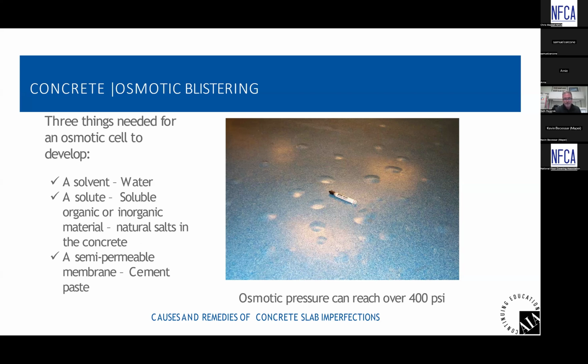So there's essentially space for that PSI, that 400 PSI, to dissipate. Well, actually, it won't ever happen, because the water and salts can go up and swim around in the new cementitious layer. Yeah. And not build up directly underneath the resin material. Right. You don't have that head pressure build up, because the semi-permeable membrane is not in that new cementitious layer. Yeah.